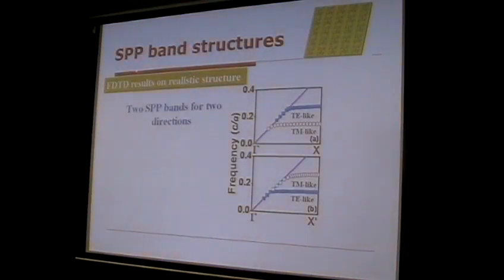Indeed, we performed FDTD simulations on the structures to calculate the surface plasmon polariton band structures of this system. And we found that we have two very well-defined surface plasmon bands for two directions. Because the structure is inherently anisotropic, the surface plasmon band for this direction, gamma to X, and for this direction, gamma to X prime, is different. However, for each direction, we found two very well-defined flat SPP bands.